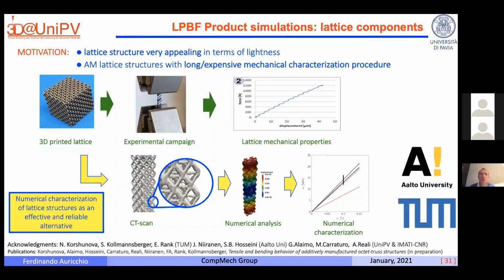And the point of view I want to show you is that the dimension of the lattice is usually very close to the precision of the technology that you use to produce your component. And this can be extremely challenging from a computational point of view. In fact, what is the experience we did? Basically, we 3D printed some lattices. We did an experimental campaign, so we got some force displacement curves, and then taking the geometry of the lattice, we ran some simulations, and from physical experiments and numerical experiments, we were getting very different results. So the mechanical behavior was far away from the predicted behavior.